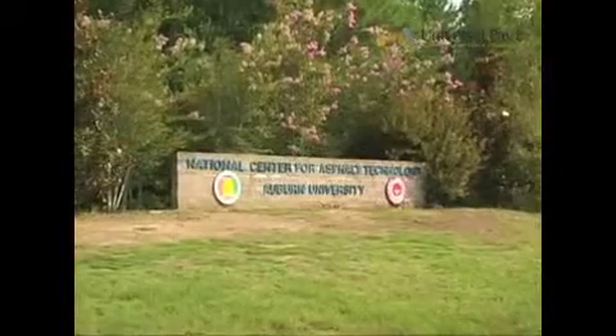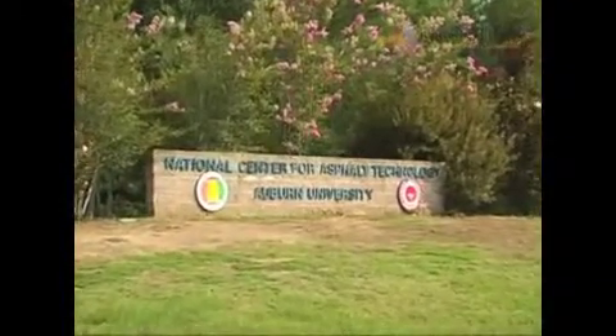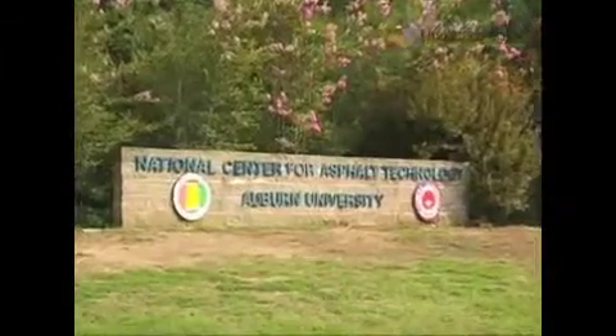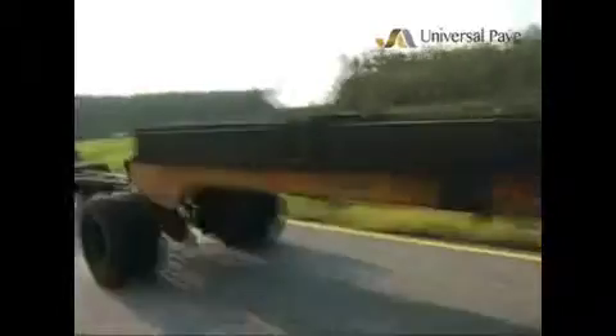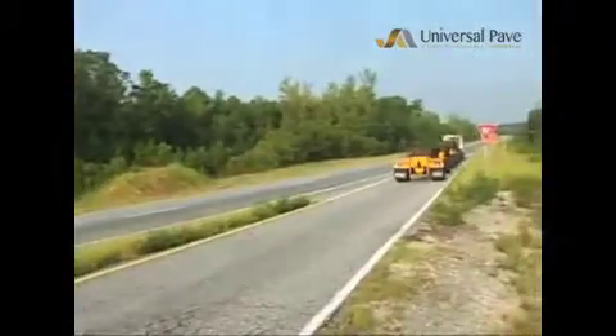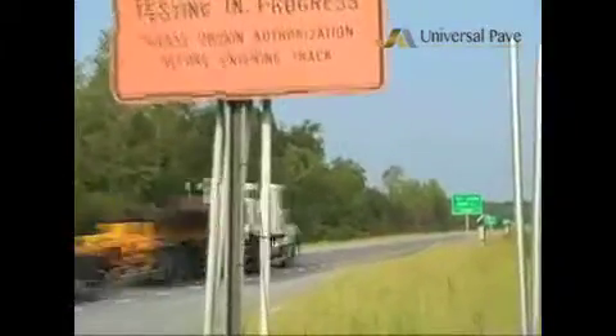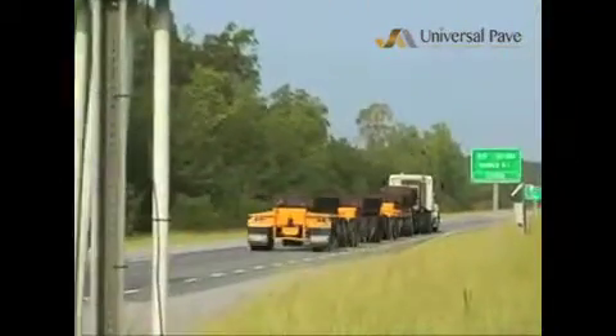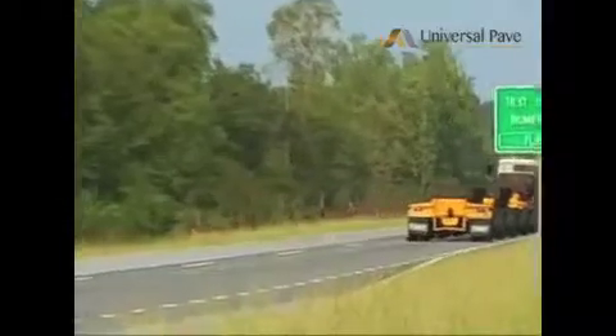You know, warm mix processes aid compaction. So the question was, would the aid to compaction continue on into traffic? This is just one of the questions being answered at the NCAT test track. After compacting the pavement at 180 degrees Fahrenheit, truck traffic was immediately returned to the track. The warm mixes have performed extremely well. There's only approximately 1 millimeter of rutting in both of the warm mix sections. You know, 1 millimeter is almost an inconceivably small depth.